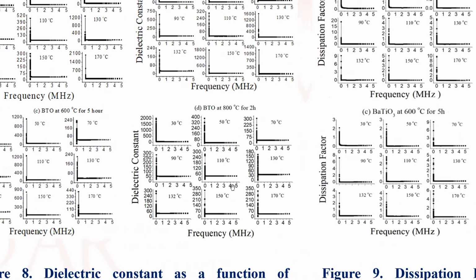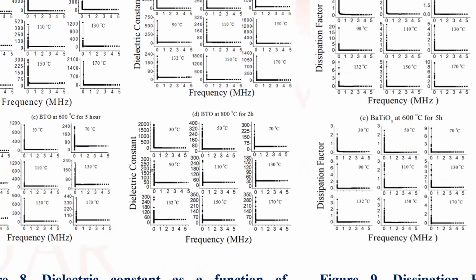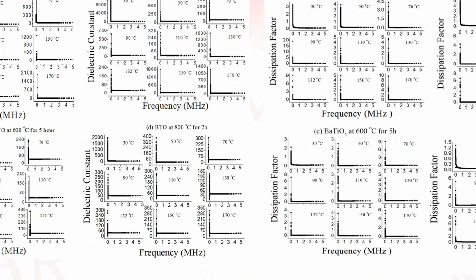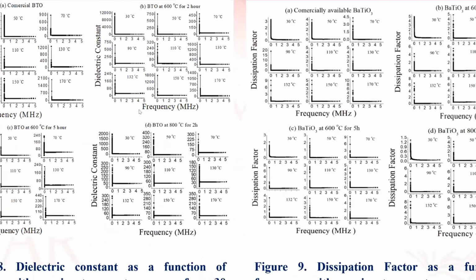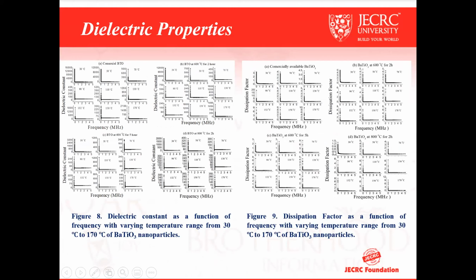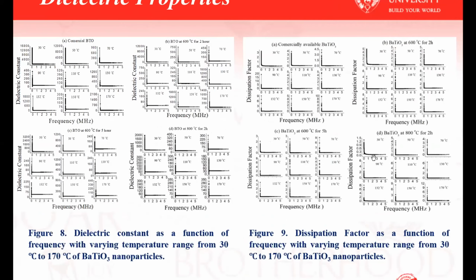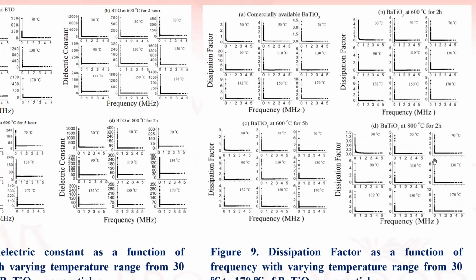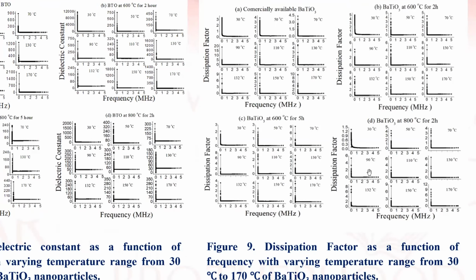So we obtain that the dielectric constant is almost constant just because the interfacial polarization stopped here. And if we see the dissipation factor also, the same property we have obtained here: the dissipation for the material calcinated at 800 degrees centigrade for 2 hours is very minimum, whereas at temperatures lower than 800 degrees centigrade, we found more dissipation.